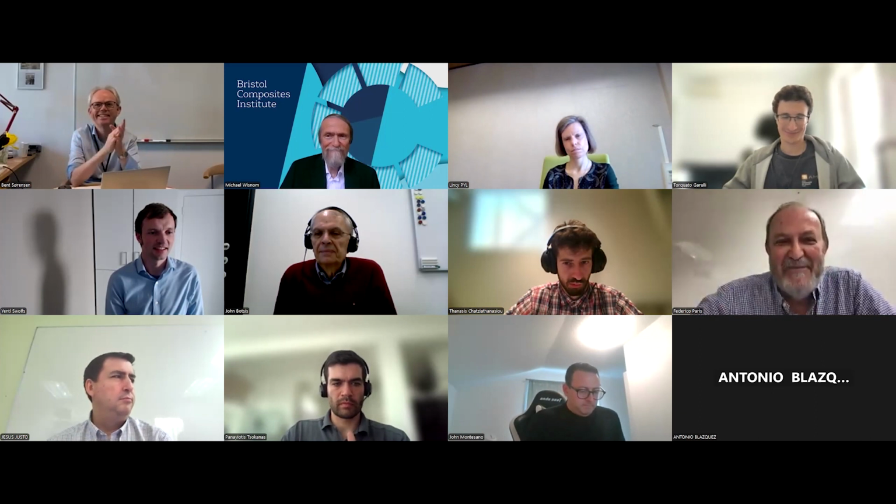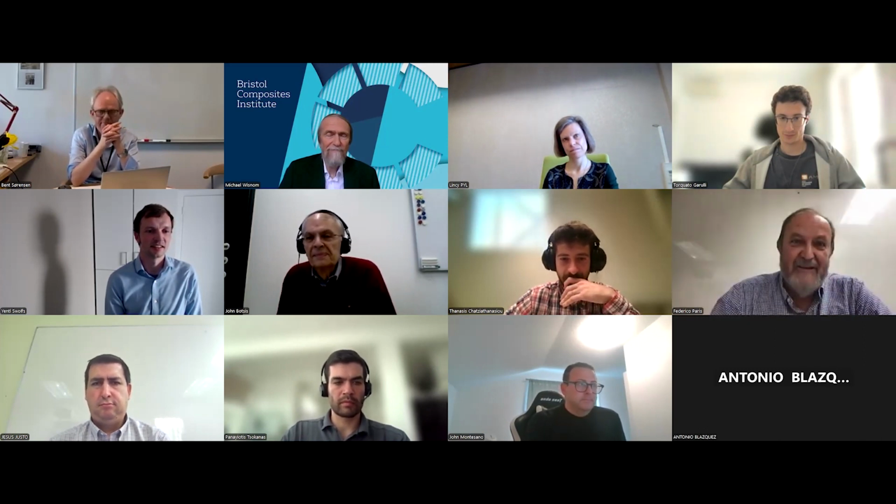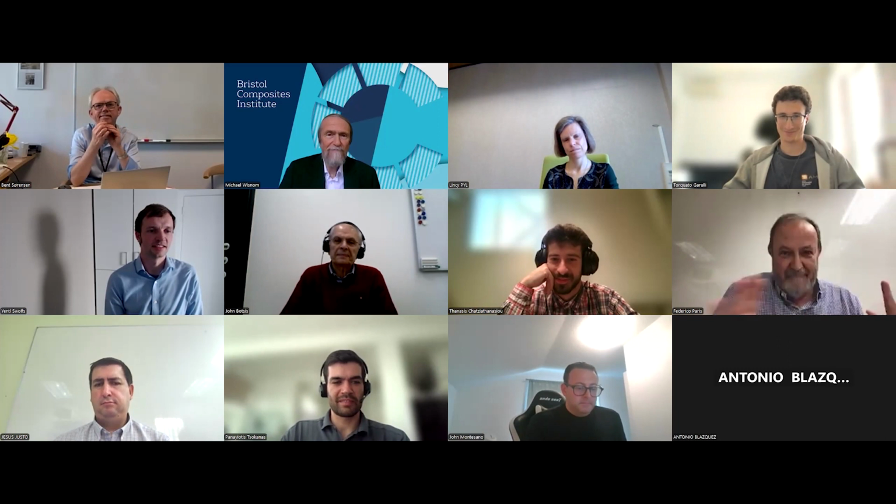Anybody else? Yes, Federico. A crack does not grow if it is not initiated. So it is very important to control the growth, but it's even more important to control the appearance. And we cannot say that the appearance is controlled by fracture mechanics theory. Fracture mechanics theory is developed to control the growth of a defect. And when we try to say, okay, this value I can use to predict the onset, no. It reminds me a little bit of the problem of short cracks and long cracks. For short cracks, we can't use fracture mechanics. Okay? Yeah. But anyway.